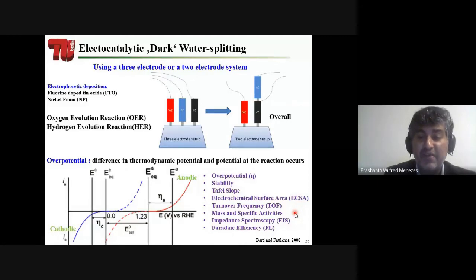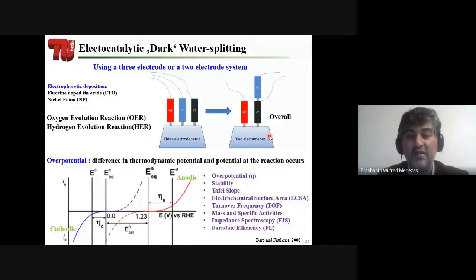Then we have mass and specific activities, how much current we can produce with how much amount of sample. And then we have impedance spectroscopy, which gives us the charge transfer resistance between the electrolyte and electrode interfaces. And finally, the Faraday efficiency, which means how much charge you put in and how much hydrogen you get out. I will not go into details because this is very complicated, but what I will show you in the coming slides is only overpotential and stability of the system. These are the most important factors to run the electrochemical system.